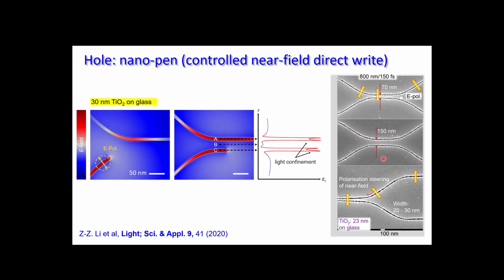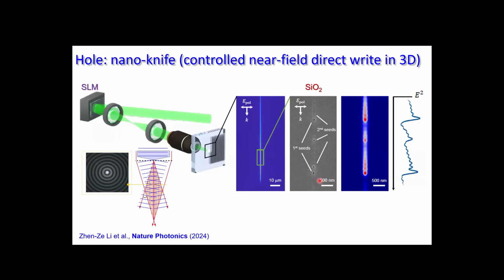And here it's really the question of resolution, because you can write two lines very close. So this is the challenge for resolution. A single feature, a single line, can always be written because of this threshold effect. But when you write two lines, then you claim resolution, and high resolution can really be obtained. Okay, so this was 2D. So we can do lithography down to tens of nanometer resolution just by direct write of a laser, which is focused on a 1 micron spot, which is kind of nice and very simple.